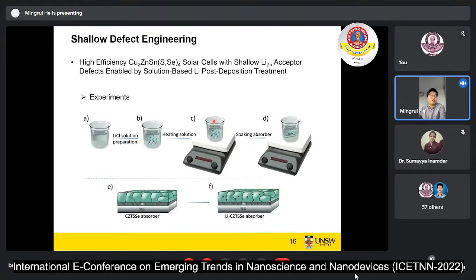I won't go into much detail for both works, so I will just introduce the key points. Here is shallow defect engineering for CZTS. Once we get the CZTS absorber by selenization, I prepare the lithium chloride solution for doping the lithium. I put some lithium chloride powder in DI water and heat this solution to 80 degrees on the hot plate, keeping it warm for about 1 hour. After that, I soak the CZTS materials for the doping.